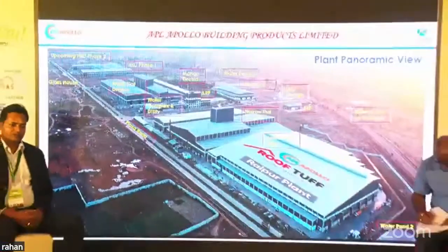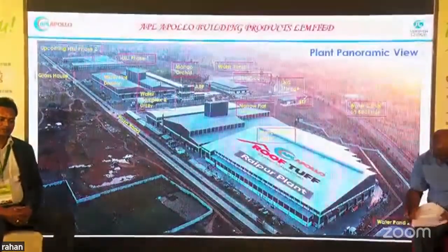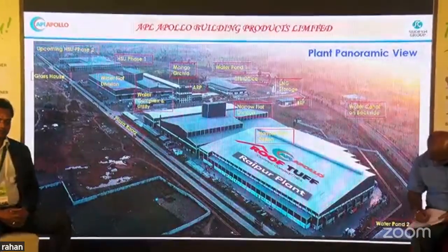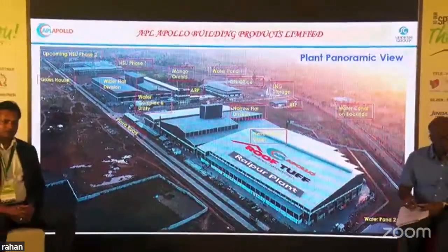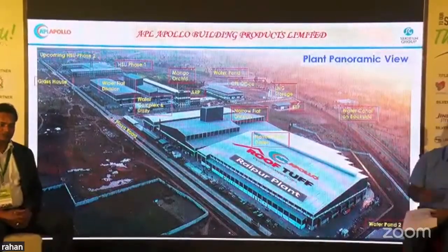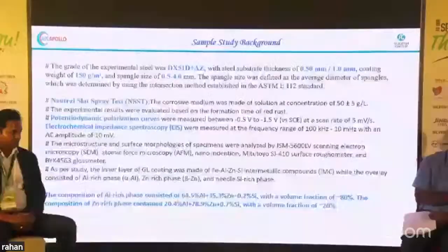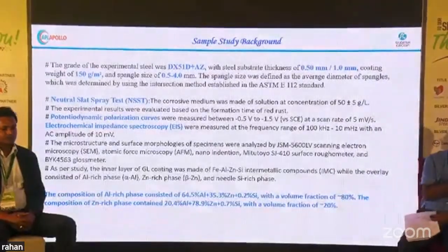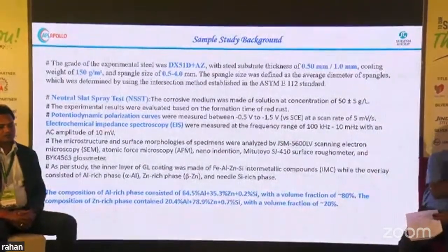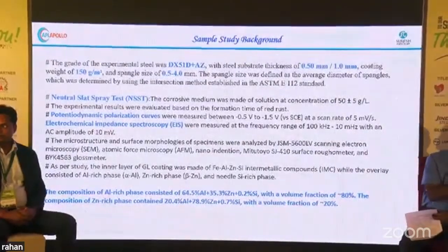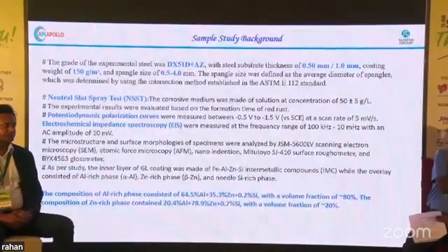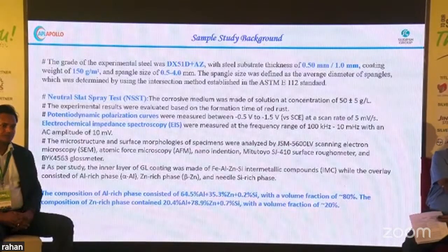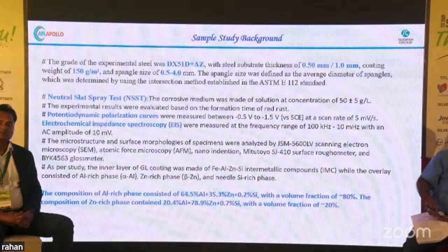So this is the overview of our company based at Raipur. This is the panoramic view. We have almost 600 acres of land, and we have 2 flat products units and 2 tubular products units. I will not go into details, already covered by our CEO, Mr. Brajesh Nahar, yesterday. Now, the sample under study had a thickness of 0.5 mm to 1 mm, the coating was AZ150, and the steel grade was DX51D as per EN 10346.